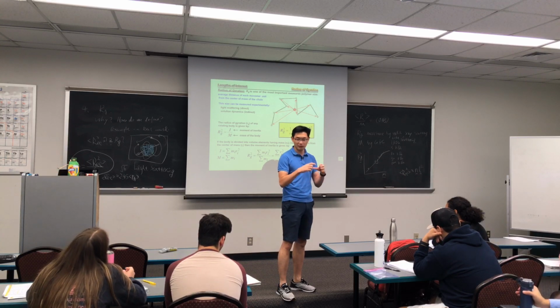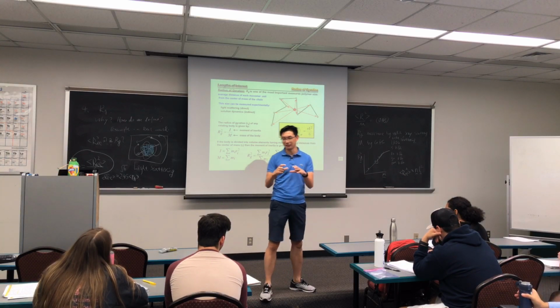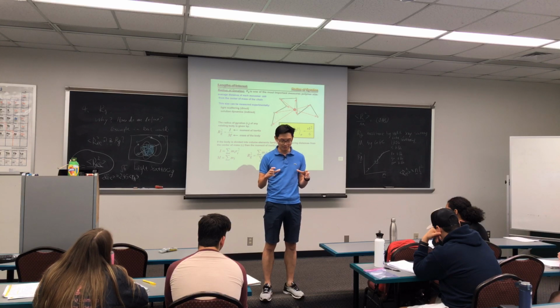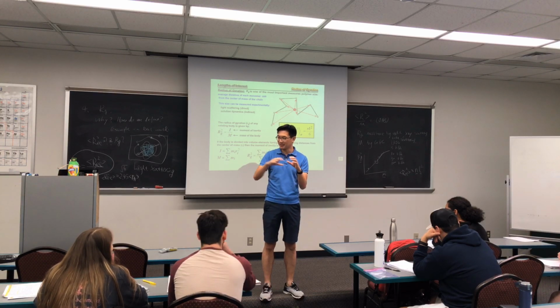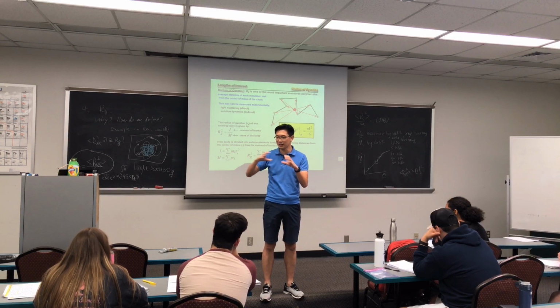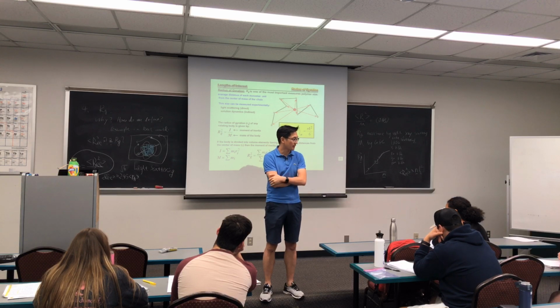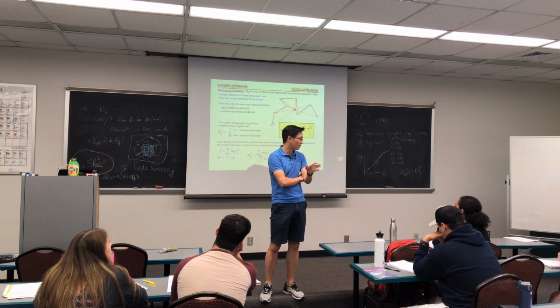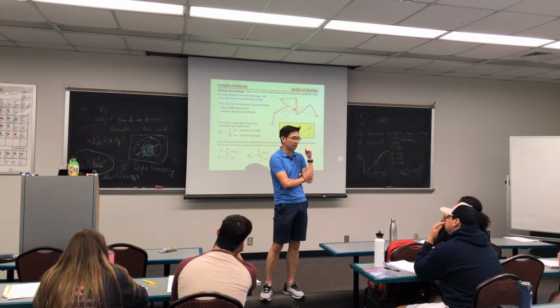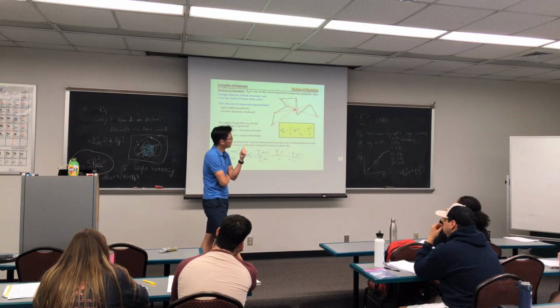Make sure your coils don't overlap each other. So in the solution, it looks like one individual chain is floating around. The next chain is so far away that all the scattering happens from the individual chain. And you can extract something called the form factor out of your chain, and that gives you the radius of gyration.